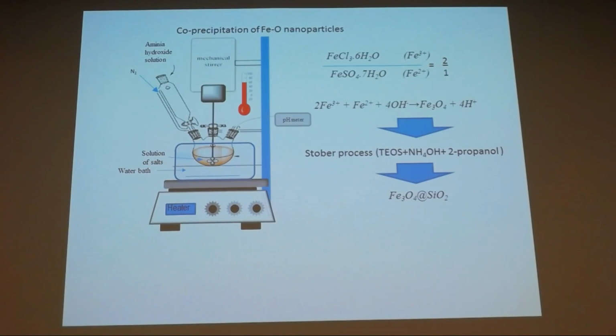For part of the nanoparticles that we collected from this process, we have done the Stöber process, which is the process to coat these nanoparticles with silicon oxide. For this purpose, we used TEOS, ammonium hydroxide, 2-propanol, and deionized water, and ultrasonicated that for 6 hours at 60 degrees centigrade.